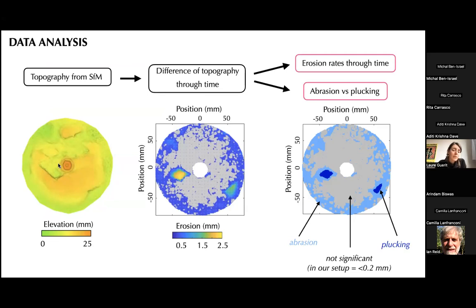Because we have temporal series of topography, we can calculate differences of topography through time and obtain an erosion map, as you can see here in the middle. So this time the color code is for erosion, so erosion between two topographies. In yellow, it means a lot of erosion. Blue is limited erosion. And in gray, it's areas that did not erode significantly between the two topographies. And in our setup, not significant means less than 0.2 millimeters.